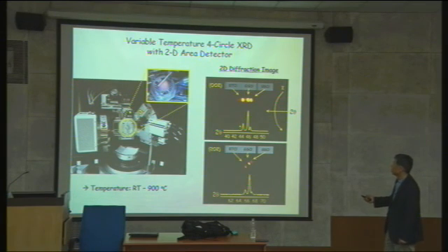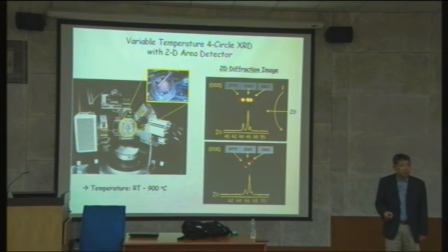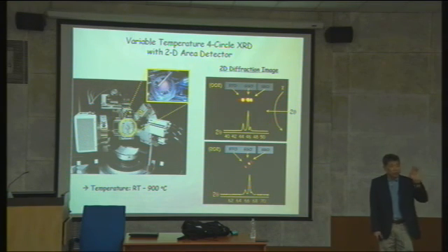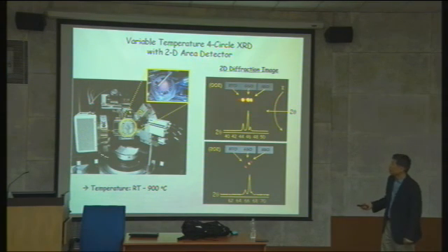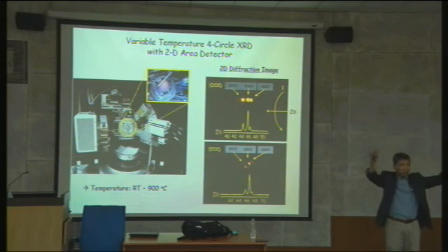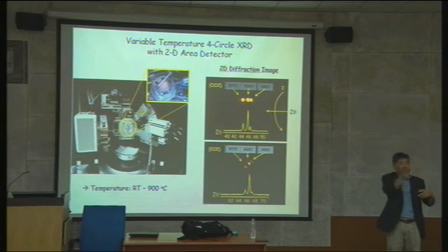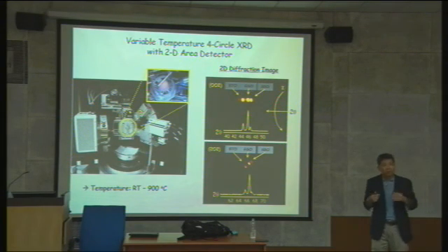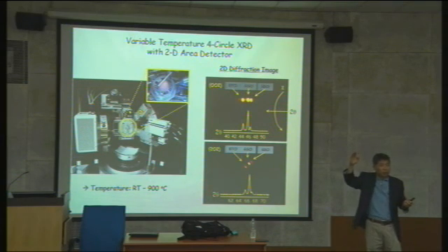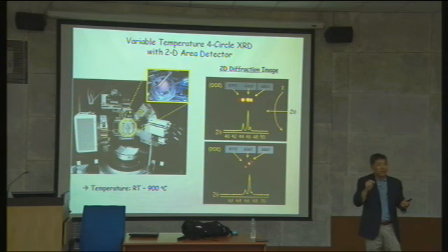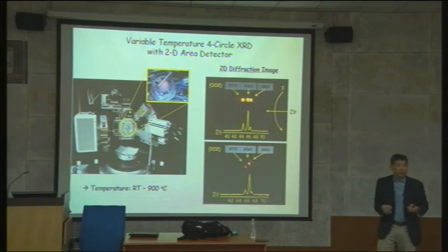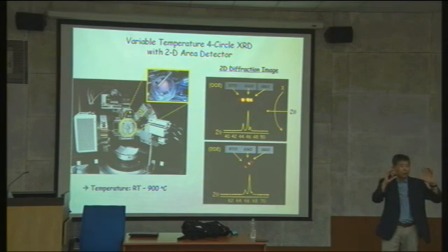And then you can see the separation of this angle here. Normally, all diffractometers use a point detector, which means your detector can only measure a small angle. That's why we call it a point detector. But here we use an area detector, which is large, so you detect all of them, two-dimensionally. Why do you want to do that? Because when you ramp up the temperature from room temperature to 900 degrees C, scanning each of them fully like you normally do takes forever, because you have to access each temperature. But here, you just ramp up and capture the whole reciprocal space at the same time.